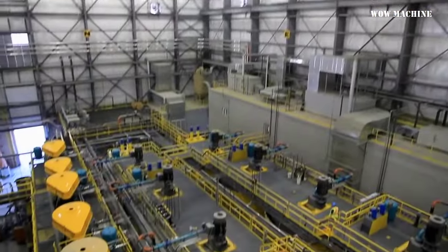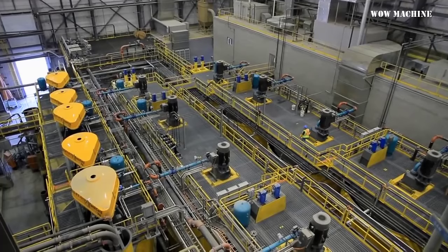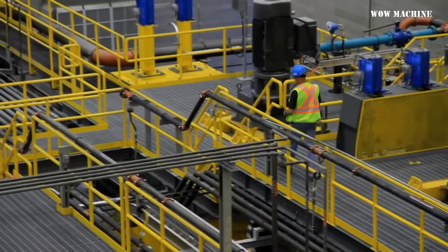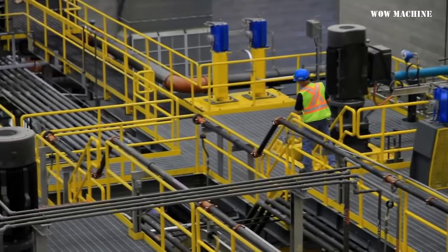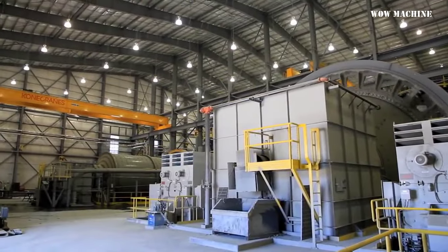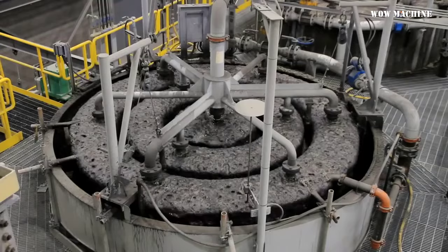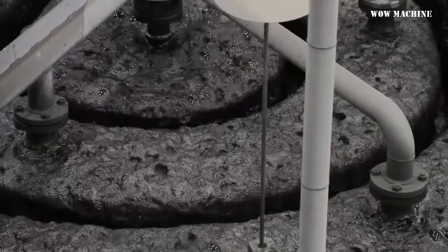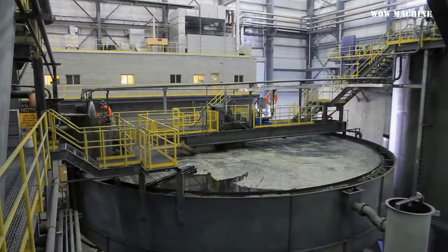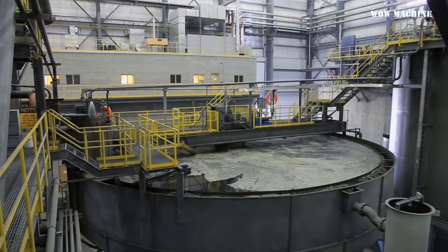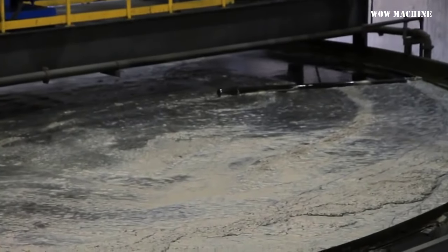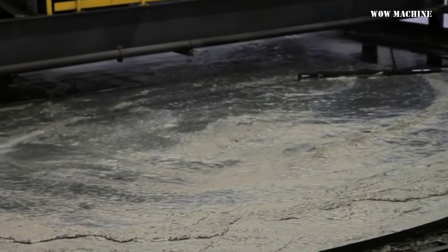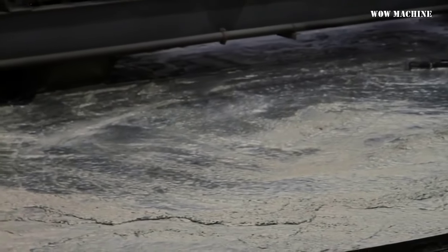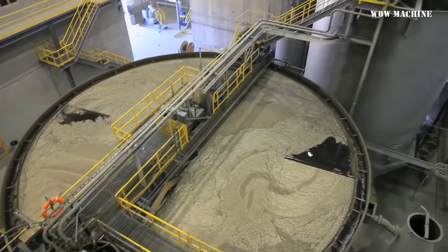The ball mills, powered by 4,850 horsepower motors, use 3.5-inch steel balls to grind the ore to a finer consistency. The ball mill product is then pumped to cyclones, where coarse material is separated and returned for further grinding, while the finer material, now ground to the size of grains, moves to the rougher flotation circuit. Here, the copper minerals are separated from the barren rock in flotation cells, where air and small amounts of alcohol create bubbles that the copper minerals adhere to, floating to the surface.